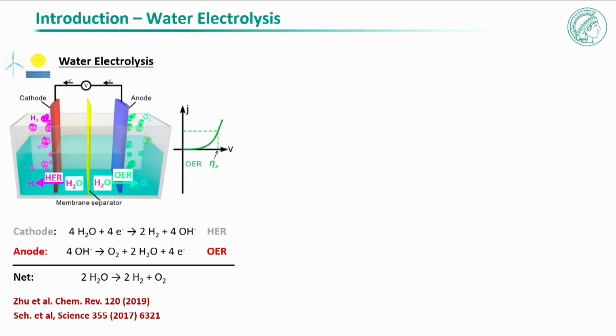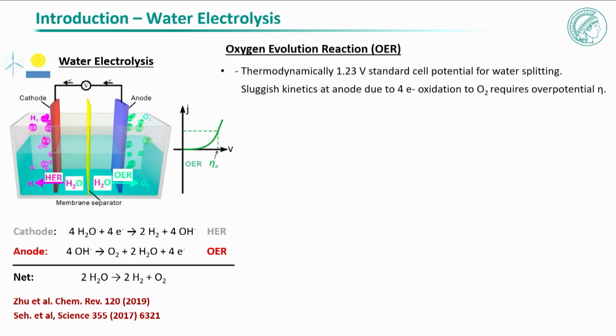So going back to water electrolysis. We have a relatively simple system. So you have here our electrolyzer. In the cathode, we are making the hydrogen with the hydrogen evolution reaction that is shown here. In the anode, we are making the oxygen with this reaction. And the hardest thing to do is the oxygen evolution reaction. This is assigned to the difficulty of the sluggish kinetics at the anode for 4-electron oxidation to oxygen. This requires an overpotential, and we are always working to try to modify this overpotential.